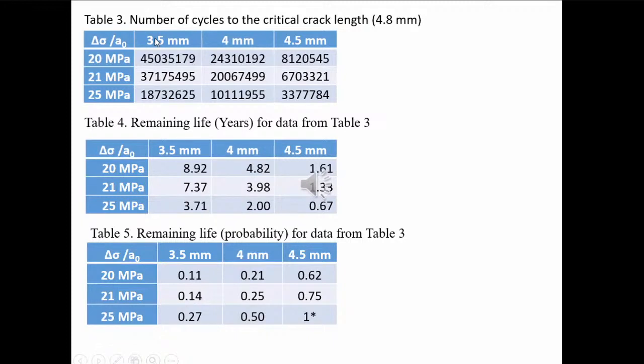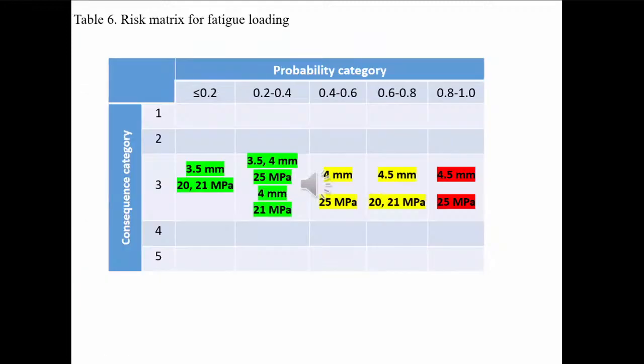So here are the results, which are in the terms of number of cycles versus critical, number of cycles versus load, cyclic load, and length, initial length of a crack. So when we put all these together in the risk matrix, we can see that we have for the consequence category 3, or moderate consequence, quite low risk for cracks which are relatively short, and then moderate risk, and then high risk for long crack, and of course high loading.